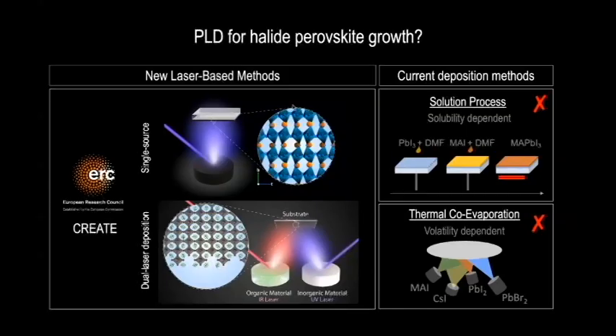Well, to switch gears towards solar cell applications, this is the work done in the research group of Professor Monica Morales. She's looking at many electro-optical materials, but also halide perovskites for use in solar cells. She's working on technology based on pulsed laser deposition to create these halide perovskites, either by using a single source, or by using a so-called dual laser deposition technique, where you co-evaporate using two lasers an inorganic material together with an organic material, and on the substrate this material should assemble into such a halide perovskite.